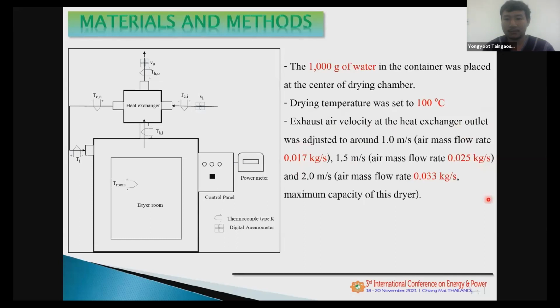Exhaust air velocity at the heat exchanger outlet was adjusted to around 1.0 meter per second, and the mass flow rate is 0.017 kilogram per second; then 1.5 meters per second, with a mass flow rate of 0.025 kilogram per second. And the last condition is 2.0 meters per second, with a mass flow rate of 0.033 kilogram per second. That's the maximum capacity of this dryer.